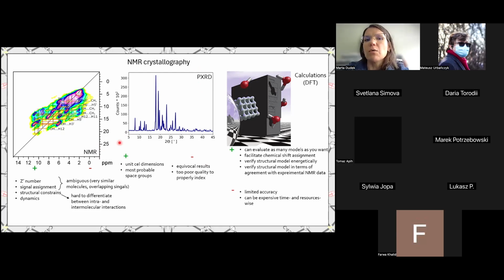So why do we need NMR crystallography at all? I think this is quite obvious for many of us. In many cases, we are not able to crystallize crystals of sufficient quality to put into a single crystal X-ray diffraction machine, so we cannot determine the structure from single crystal X-ray diffraction. This is definitely the method of choice, but it cannot always be used. It is also not that efficient in establishing hydrogen atom positions, for which I will be showing examples in a second.